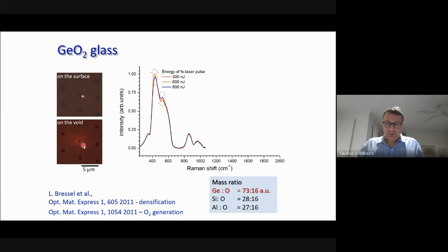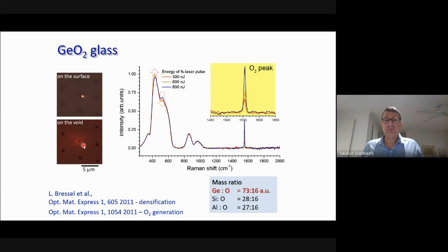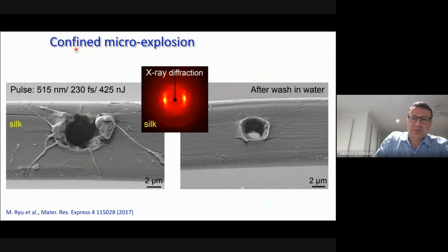So we fabricated some voids inside glass, and then we looked for Raman scattering. And we looked in the region where nobody usually looks, because it's not interesting. There is nothing happening in glasses there. But in fact, if you really focus on the modified area, you can see that depending on pulse energy, which is opening the size of the void, you will see that oxygen is in that void. So this is the proof that with the energy you deposit, you are cutting chemical bonds, and you are ionizing material. And in this case, we saw oxygen in a much simpler experiment.